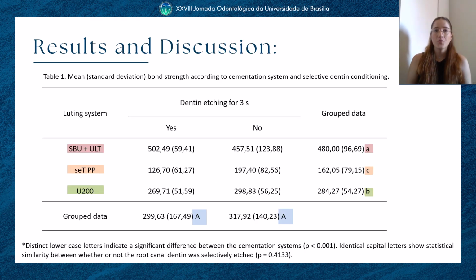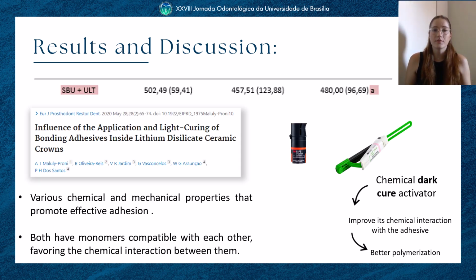Regarding the results, in Table 1 we can observe that there was no difference in terms of dentin etching. For the luting systems, SBU plus ULT presented the best bond strength values, followed by U200 and seT PP. The better result in the SBU plus ULT groups can be explained by their various chemical and mechanical properties that promote effective adhesion. Also, they both have monomers compatible with each other, favoring the chemical interaction between them. Finally, the ULT presents a chemical dark cure activator that improves chemical interaction with the adhesive, promoting better polymerization.